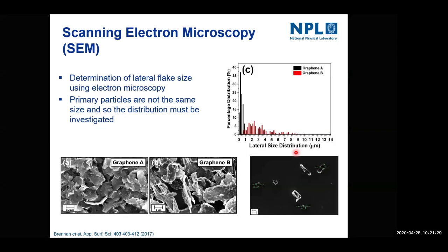One of the options, once we've isolated these flakes on a substrate, is to look at microscopy. One of the routes uses SEM to start with. Scanning electron microscopy essentially bombards the surface with electrons and looks at the scattered electrons to get an image. You can see these images down below, very high resolution nanoscale images. What we're getting from this technique is the lateral flake size. So again, you can see we have flakes here, finite-sized, lateral dimension-sized particles, in this case the shape of flakes.